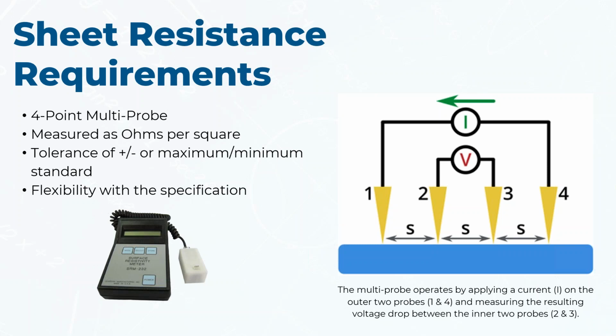Commonly, sheet resistance requirement is specified as a maximum or a minimum. And then you can get into megaohms. Megaohms are typically used in electrostatic discharge. Low ohm coatings, like 4 to 6 ohms per square, are used in electromagnetic and radio frequency interference filters. So what you're trying to do here is basically tell me how much pulsed electricity is going across the surface and how that's going to interact in my environment.